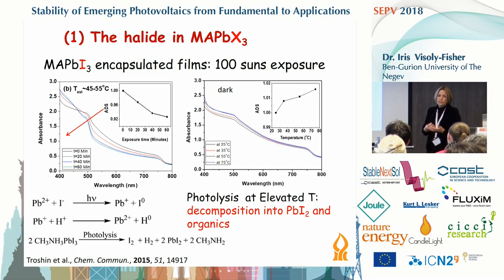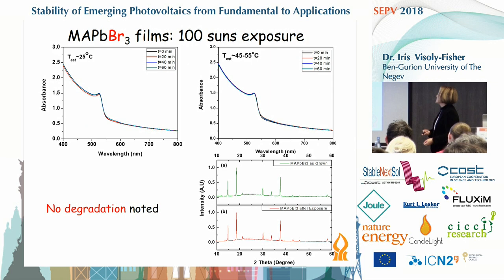And this is not very surprising. There have been quite a few mechanisms, and we all focus on the same result. There is photolysis at elevated temperatures of MAPI, and it decomposes into lead iodide and some organics, and this is well known, only we could show it within an hour. That's not too surprising. And then we moved on to the methyl ammonium lead bromide films, and repeated the same kind of experiment,